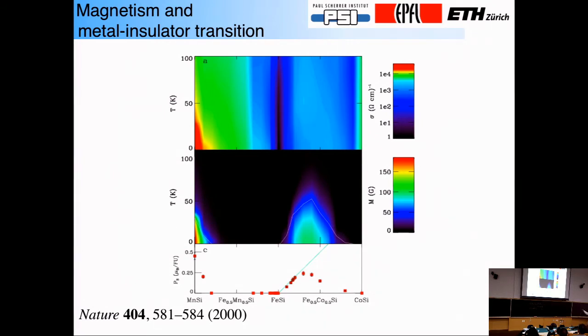So I'm not just flashing view graphs. What you see here is the conductivity. Here you see a parent compound, which also actually happens to be a silicide. Conductivity is very low here, black, near zero. It's an insulator. And then as I dope this insulator, in this case with cobalt, I induce a metallic phase, but also a magnetic phase. So this is another phenomenon that coincides with a metal insulator transition, not something you would find in silicon, but nonetheless related.